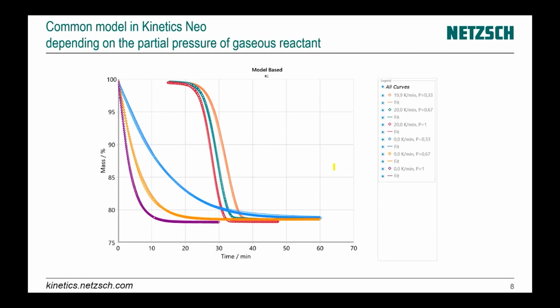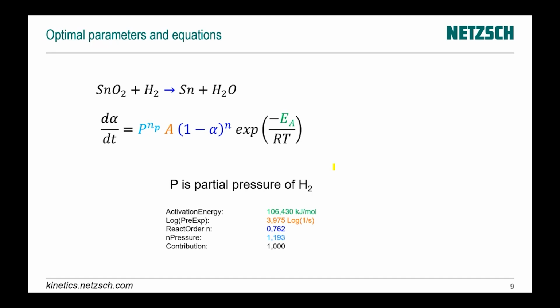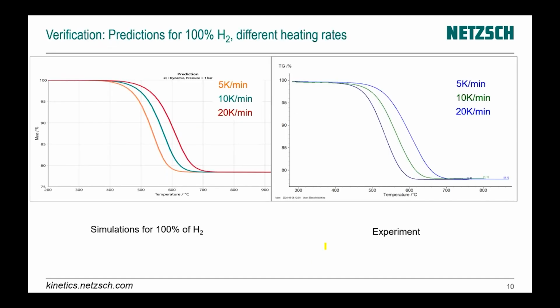And again, here is our result. After optimization of all parameters, we can find the activation energy, the pre-exponential factor, the order of reaction, which is 0.7, and the order for the partial pressure of hydrogen, which is 1.2. For verification of this model, we did additional measurements and additional predictions.